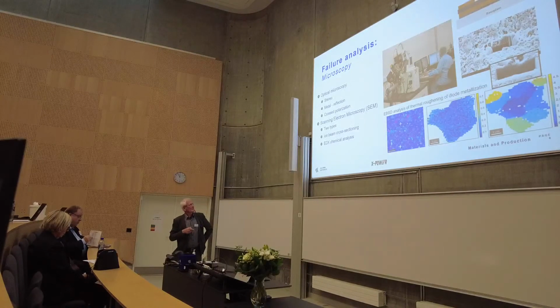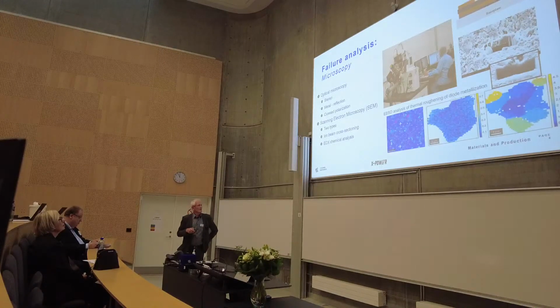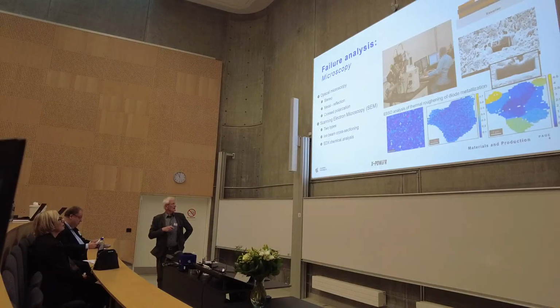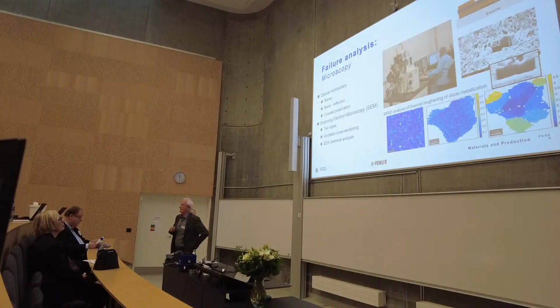This one has also an ion beam sitting here, so you can actually cut into something. Here's an example. You cut through the metallization of a diode, and you can go in and analyze the cross-section. And afterwards, you can do a chemical analysis, spatially resolved with the electron beam, because it generates X-rays that come up to an X-ray detector that sits there.